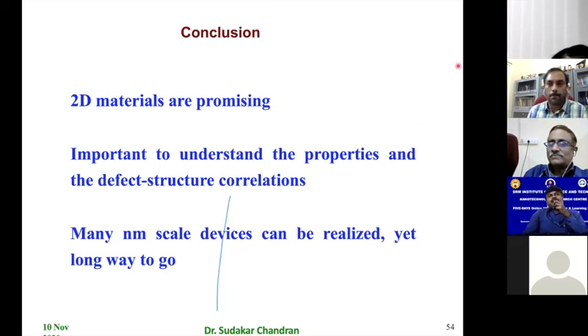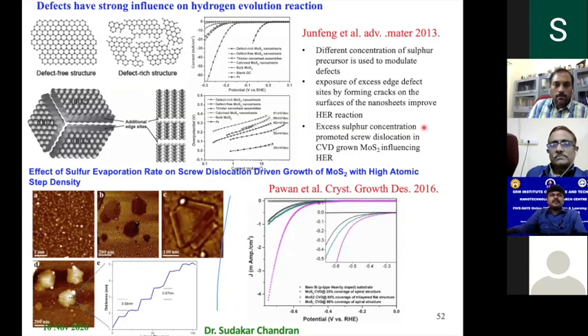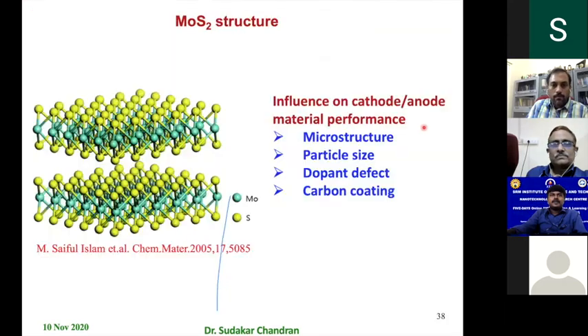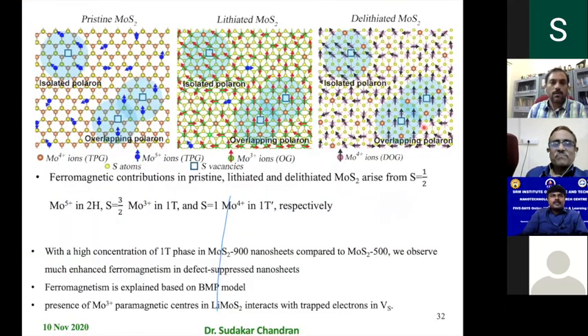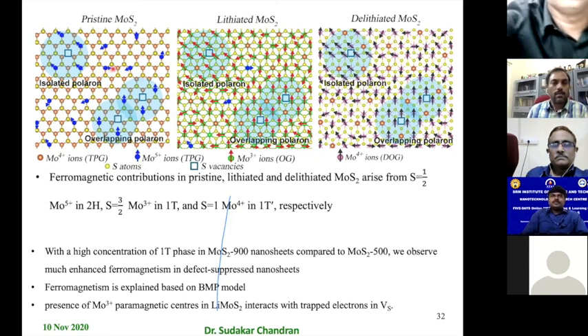What is the origin of magnetism in this MoS2? As I said, if we go back to that, maybe this particular slide will explain. So dilute magnetic semiconductors, are you familiar with them? In oxide systems, when you have transition metal dopants, the magnetic interaction through the magnetic polarons gives rise to a long range order. So for example, here you have these paramagnetic sites, right? They are scattered. Generally, if you have defects, they'll be paramagnetic in nature.